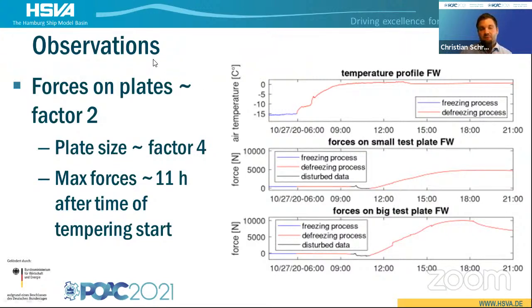If we now come to the observations compared to probably our initial expectations or ideas, we saw that the forces on the test plates had a factor of about 2, so 5 kilonewtons to about 10 kilonewtons, but the plate size factor is around 4. And the maximum occurred forces could be measured after about 11 hours when the core temperature of the ice was in the region of melting temperature.